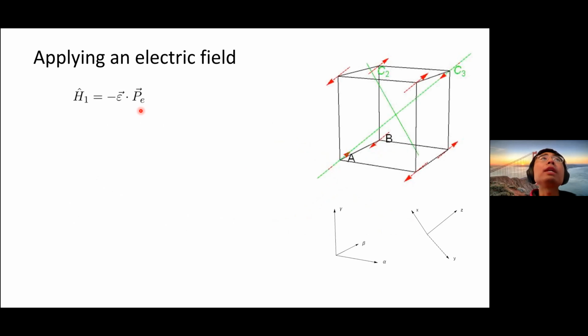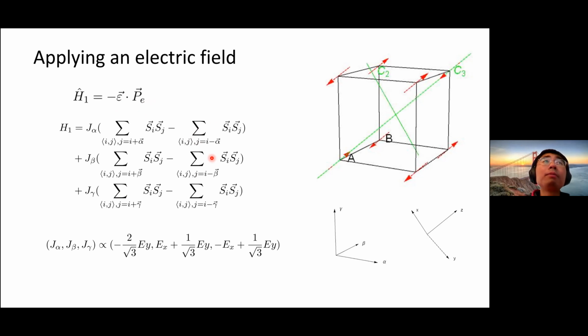Typically in a magnetic system, where the low energy degrees of freedom are spins, the electric dipole moment is typically bilinear in spin. Here, by symmetry analysis and some perturbation theory calculation, we can obtain the form of the coupling of the spin system to the external electric field. So generally, this is the form of the Hamiltonian in this case.